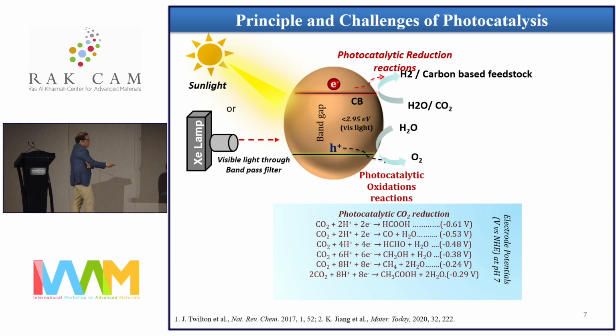I want to bring your notice here. Let's say CO2, when it undergoes 2-electron or 2-electron 2-proton reduction, forms CO, and you can see the reduction potential in this is minus 0.53. But if you look at CH4, the reduction potential is minus 0.24, which is thermodynamically a more facile process. But if you look at the number of electrons, it's an 8-proton, 8-electron process. This means the kinetics of the electron transfer has to be much higher in this process.